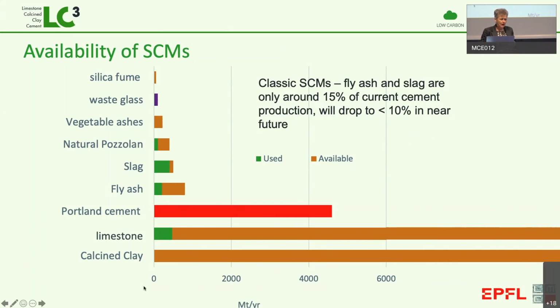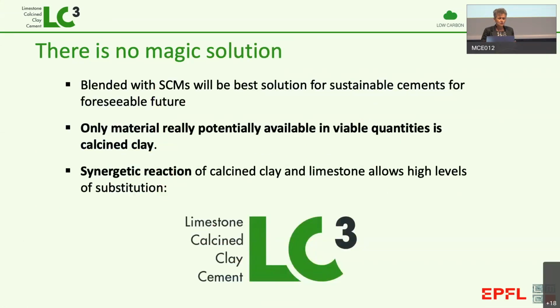And the one thing we do have, which is a real game changer, are clays. Clays are super abundant, they're available everywhere, and they can be simply what's called calcined, that's to say heated, in the range of only about 800 degrees, so much lower than making cement. And this is what led us to this technology we call LC3. LC3 stands simply for limestone calcined clay cement. We started off calling it low carbon cement, and then we realized everybody was calling their solution low carbon cement. So we just wanted to be factual.